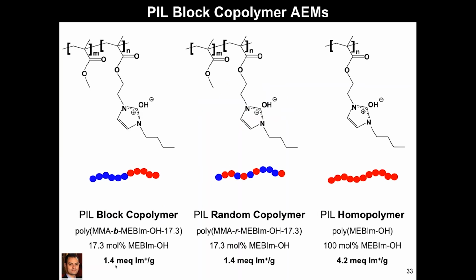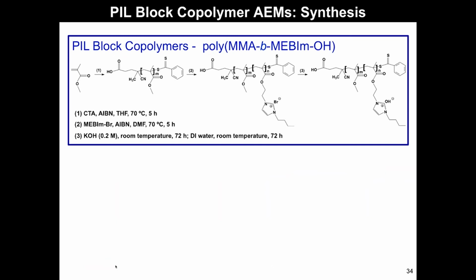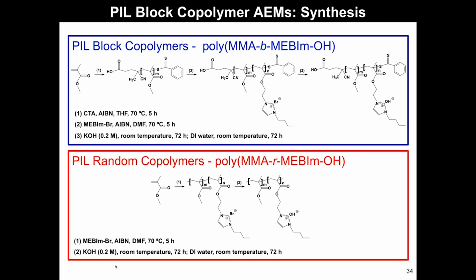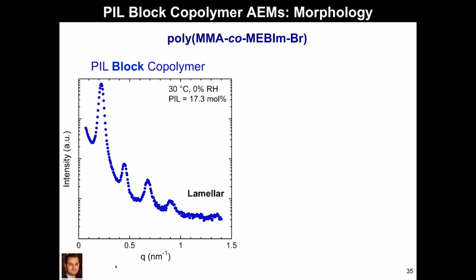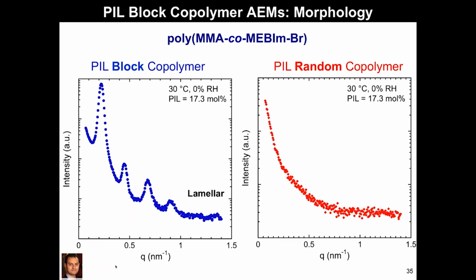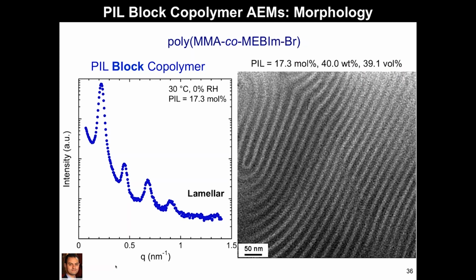One of the things that we did was a controlled study of making a block copolymer or random copolymer at the same exact composition and charge density. We made block copolymers here using the RAFT procedure, and we made random copolymers using free radical polymerization. And you can see here, as we would expect from a block copolymer, you can get phase-separated morphologies. At this composition, we saw a lamellar morphology, and with the random copolymer in the small angle X-ray scattering, you see no defining peaks, so there's no structure at all. And here's a TEM confirming this lamellar structure.